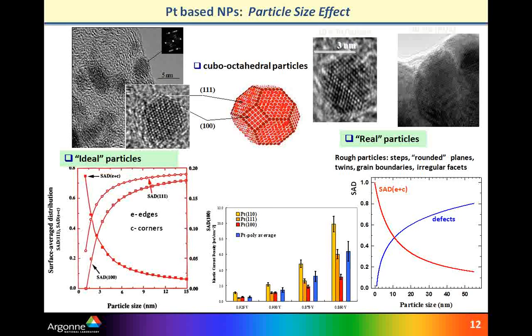But the fundamental explanation comes from the fact that in catalysis, something which is definitely well established and nobody has doubts about is that structural composition is very important. So different single crystals of platinum have different specific activity, and therefore we believe that the particle size effect comes from the contribution of different facets that are exposed at the surface. That would be a simplified and short explanation.